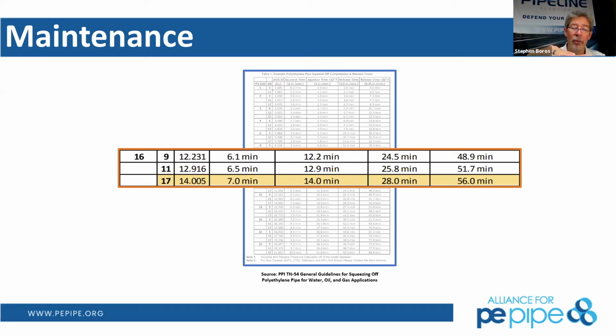So it's fairly slow. You squeeze the pipe off, it stops flow, you do your repair, and then you have to release that squeeze. Well, that's the most critical part of this whole process. And that's when damage can occur, is actually when you're releasing it and not giving the compressed material enough time to stretch and relax and not overcome its strain capacity at that point. So the rate of release of that squeeze tool is now a 1/2 inch per minute. So on 16-inch pipe, that can take up to 28 minutes.